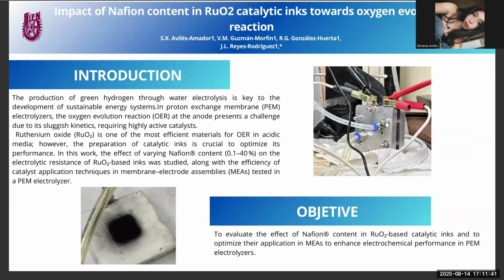As you know, water electrolysis is one of the cleanest ways to produce hydrogen. In PEM electrolyzers, the oxygen evolution reaction, or OER, happens at the anode. However, this reaction has slow kinetics, which means we need highly active and stable catalysts to make it more efficient. Ruthenium oxide is one of the most promising catalysts in acidic media because of its high activity. One key component in these inks is NAFION, an ionomer that improves proton conductivity, but its amount can also affect catalyst dispersion and block active sites.